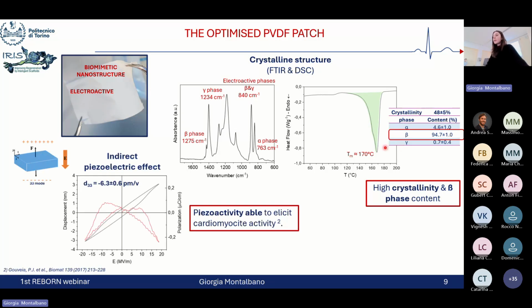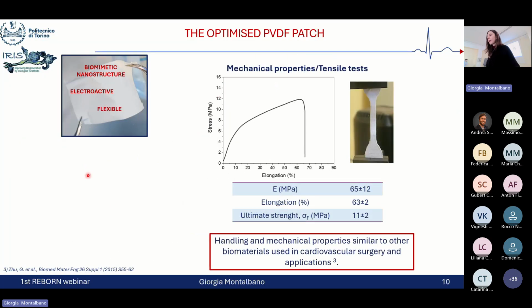We could also perform some quantitative analysis via the measurement of the indirect piezoelectric effect and the definition of the piezoelectric coefficient that could identify values that are reported to be supportive of cardiomyocyte activity according to different data reported in the literature. So overall, all these data could confirm the effective electroactivity and bioactivity of our substrate.